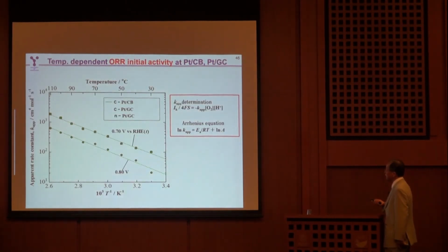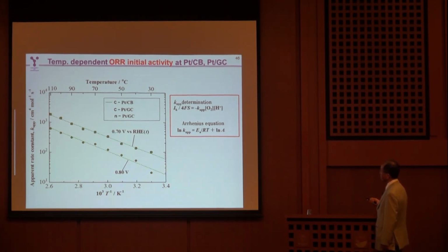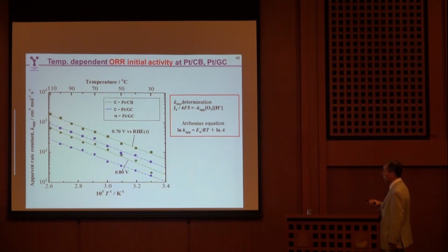But anyway, this shows the temperature-dependent oxygen reduction reaction activities, first on the commercial carbon black. And next, the blue one shows the commercial graphitized carbon. The catalytic activity is about 2 times less. But the nanocapsule catalyst shows almost the same catalytic activity as that of the commercial carbon black supported catalyst.